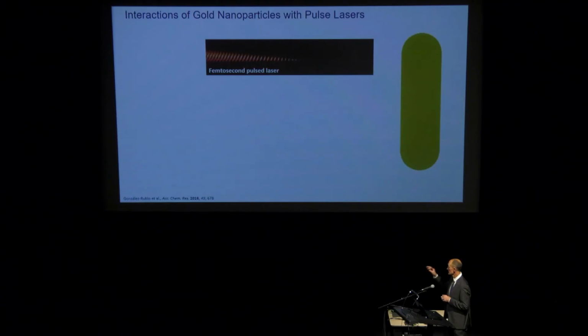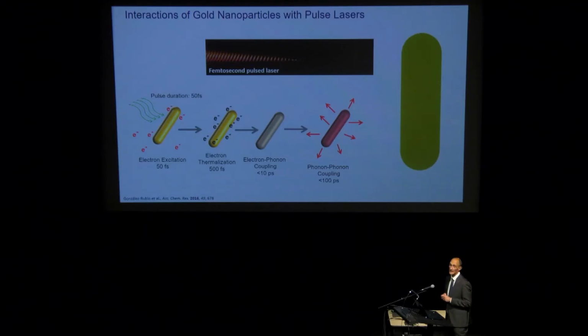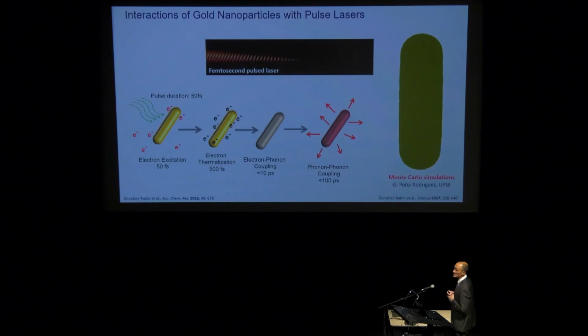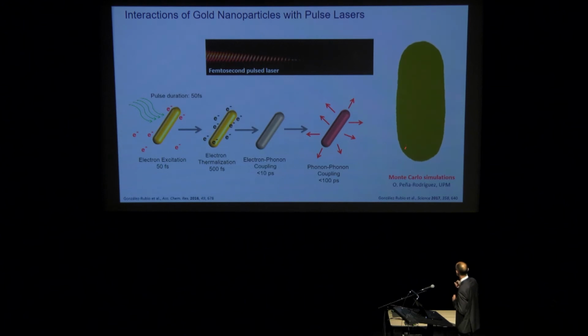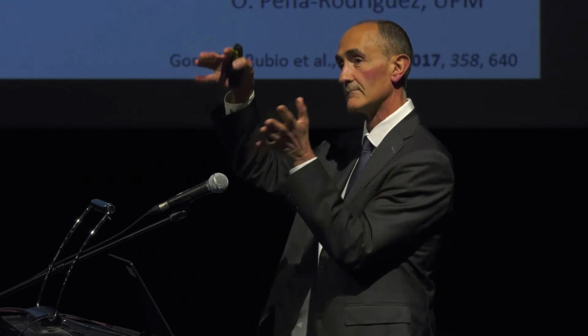And so this was when Guillermo was doing his PhD with both of us. And they were exploring the effect of femtosecond lasers on nanorods through all these mechanisms that, again, inject energy into the metal. Part of the energy is released to the solvent. Part of the energy can be used to slowly melt the metal and reshape it into an equilibrium geometry. And so these are actually Monte Carlo simulations of what happens when you're injecting femtosecond pulses into a metal particle with enough energy that each pulse is actually promoting a small reshaping of the nanorod.